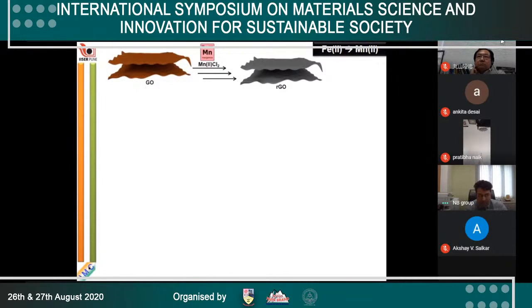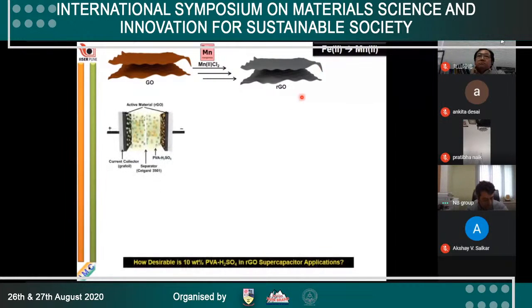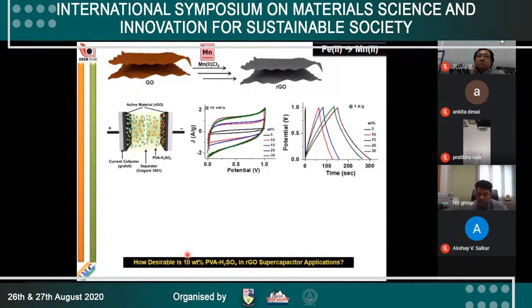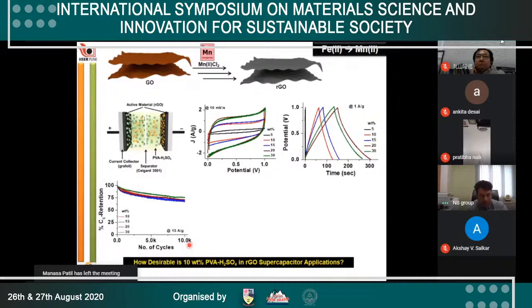We move ahead and use manganese 2 salt, and again consistently isolated good quality RGO. Now if you look at the literature, you will realize that researchers are using 10 weight % PVA to support gel polymer electrolyte. The question is, how desirable is this? So we thought to vary the weight percentage of this electrolyte and evaluated the supercapacitor performance.